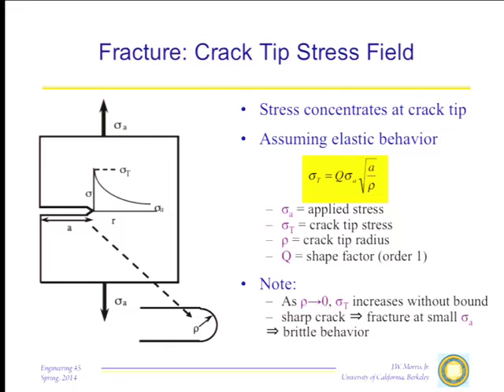So suppose that I take a sample here, and in the sample I have a crack. Now let me load the sample up with some external stress that, if this sample were complete, as we did in the first E45 lab, would be the nominal applied stress. Well, now the applied stress is fine as long as the body is contiguous. But right here at this crack, for geometric reasons, the solutions of the equations of elasticity give you a great big boost, a substantial intensification in the stress here at the crack tip. In fact, if your applied stress, just the nominal load divided by the area of the sample, is sigma A, the stress at the crack tip turns out to be sigma A times a geometric factor, the square root of a over rho. Here a is the crack length. I think in these slides sometimes I use a and sometimes I use c. And rho is the crack tip radius. What I mean by that is if you take any real crack, no matter how sharp it looks, when you blow it up in a microscope, you'll see the tip is curved, and there's some effective radius rho.